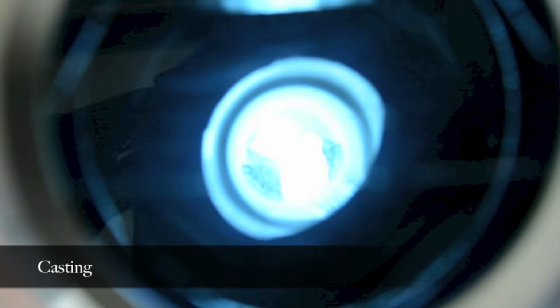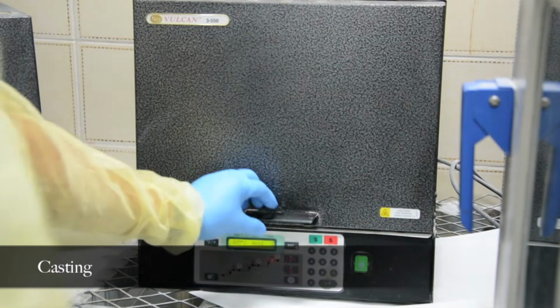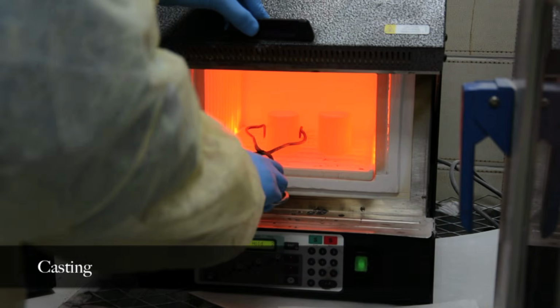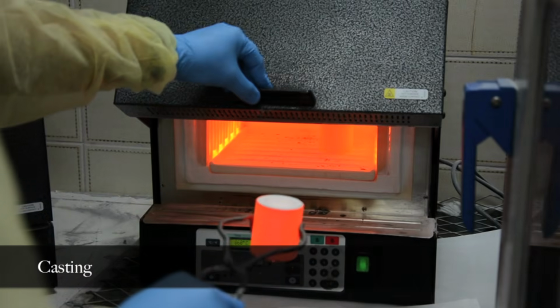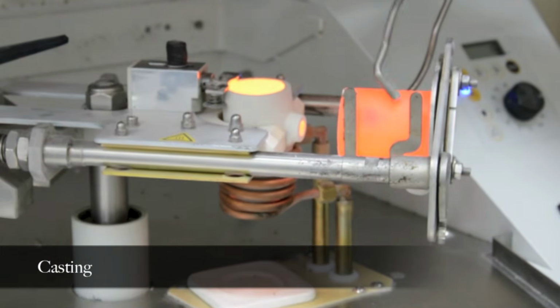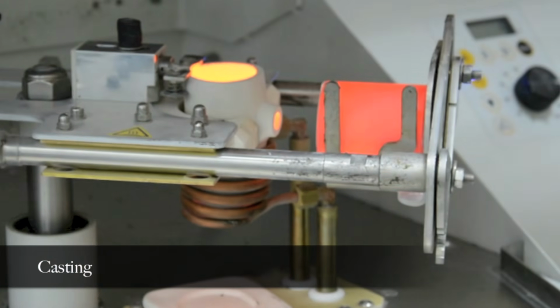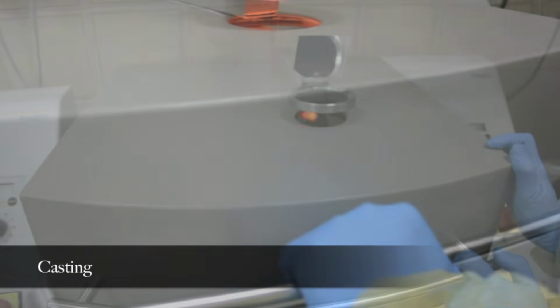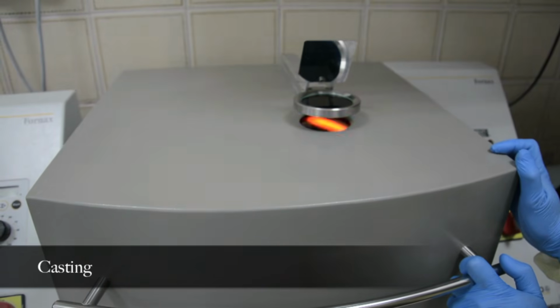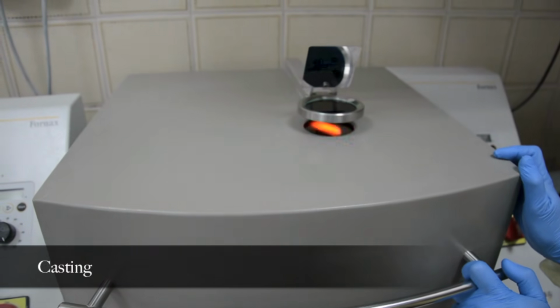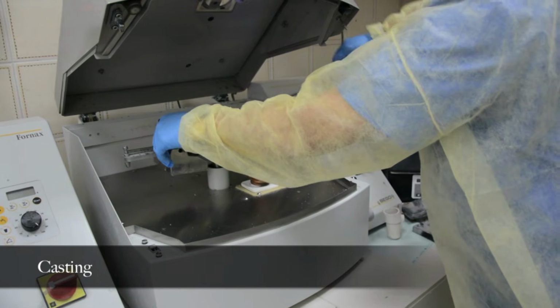No more than 30 seconds should be allowed to elapse between the time the ring is removed from the oven and the molten alloy is centrifuged into the mold. Any undue delay will cause heat loss and resultant mold contraction. The mold is placed in the cradle of the casting machine. The machine is allowed to spin until it has slowed enough that it can be stopped by hand, and the ring is removed with casting tongs.